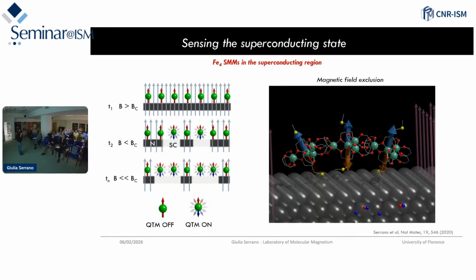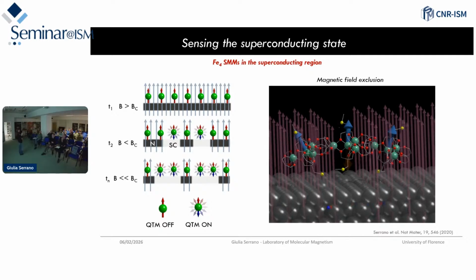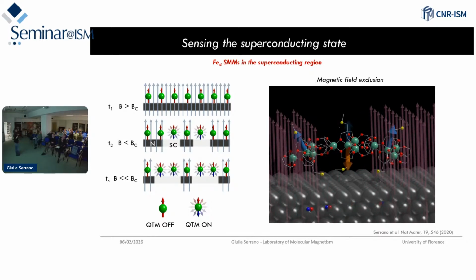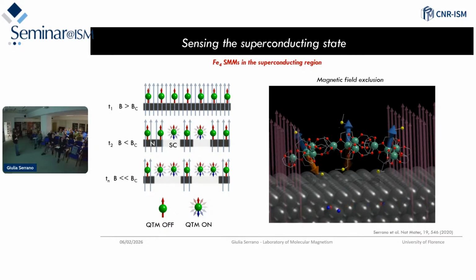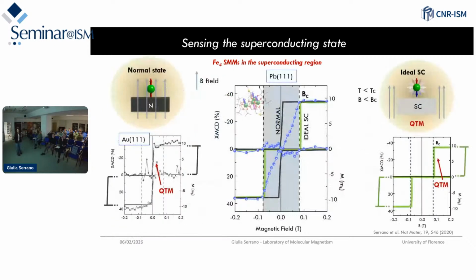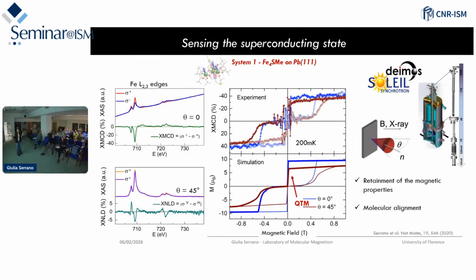It is independent of the frequency in the regime that we have, because of course the magnetization of the molecule has a decay, so it will last for some hours, but we are well below this time. So you can a little bit smooth or make more sharp these edges, this jump, when you go faster, but you don't see a decay that is due to the molecule. So that decay was actually due to the superconductor.